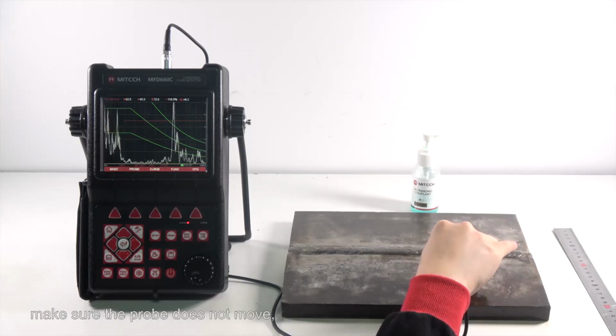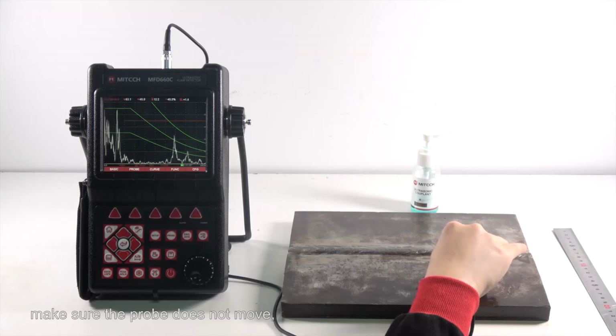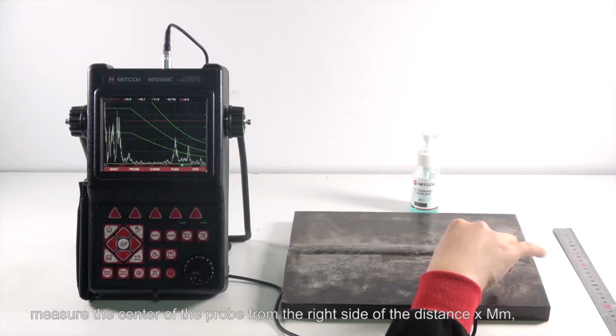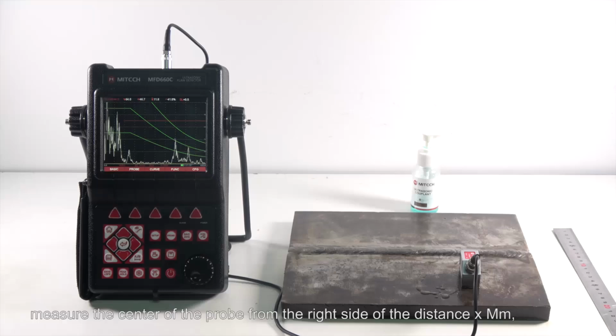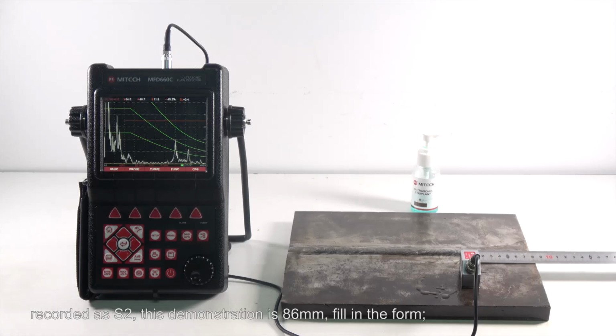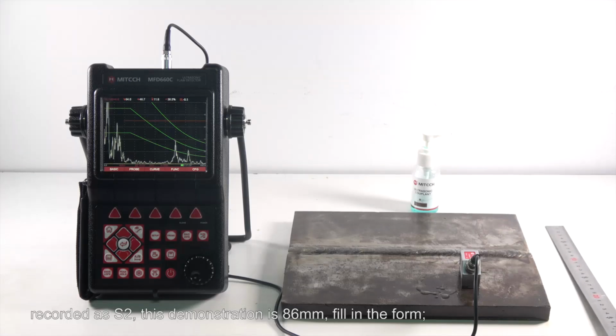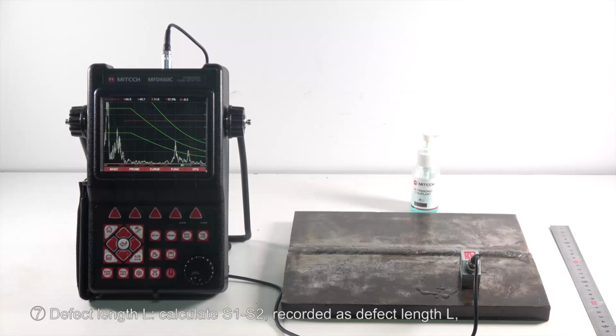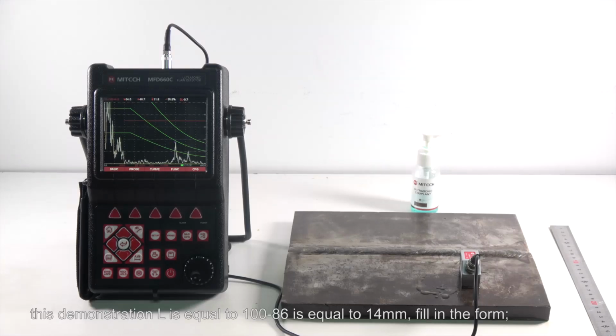Make sure the probe doesn't move. Measure the distance from the center of the probe to the right side, X millimeters, recorded as S2. This demonstration is 86 millimeters. Fill in the form. Defect length L: calculate S1 minus S2, recorded as defect length L. This demonstration L equals 100 minus 86, equal to 14 millimeters. Fill in the form.